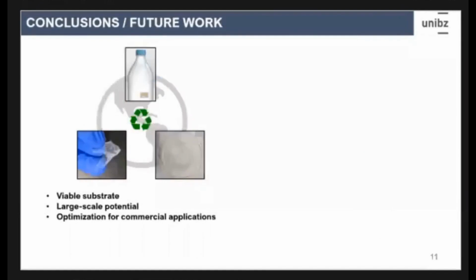So in the end, to conclude this work, we found that we can use this chemical recycling technique as a viable solution for the plastic problem, not necessarily creating more plastic and throwing it into the world, but reusing what is already here and developing a platform to keep using the plastic that is already here to reduce the impact, because this field will be increasing very quickly, and we're going to be seeing a lot of devices everywhere soon. We also found that there's very large-scale potential for this technique, since you're melting the plastic and you can give it any shape that you want. And there are also opportunities for optimization and developing commercial applications with this technique.